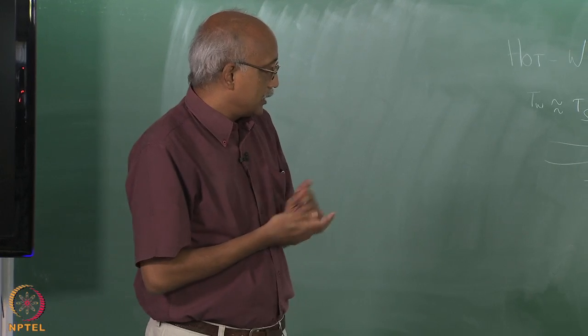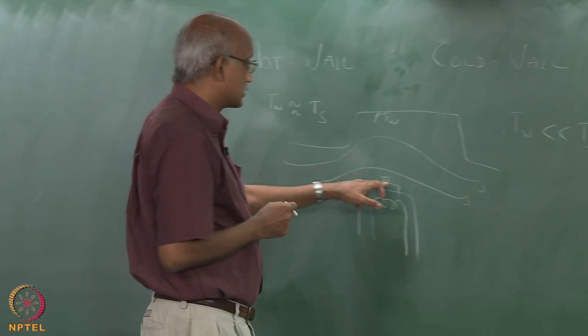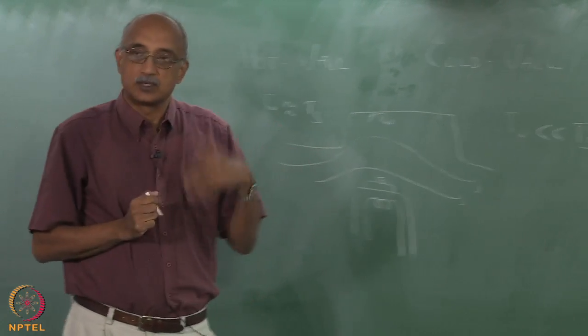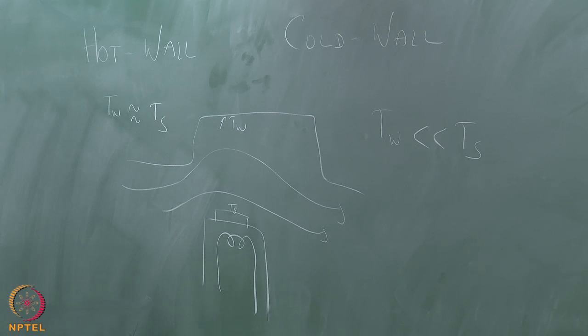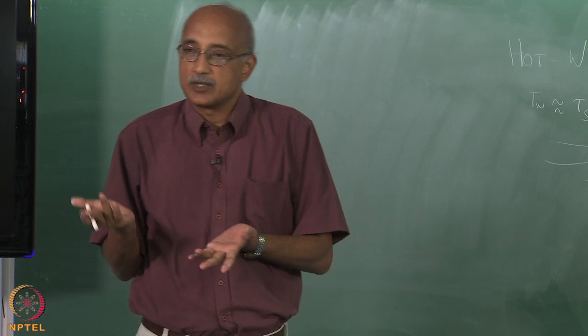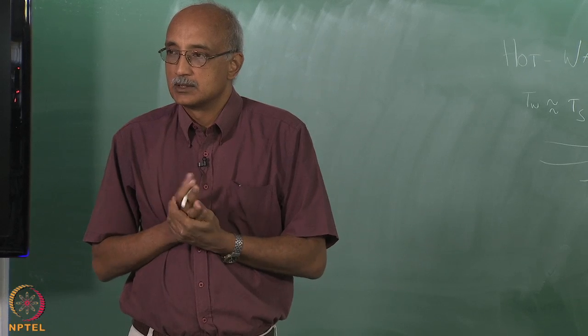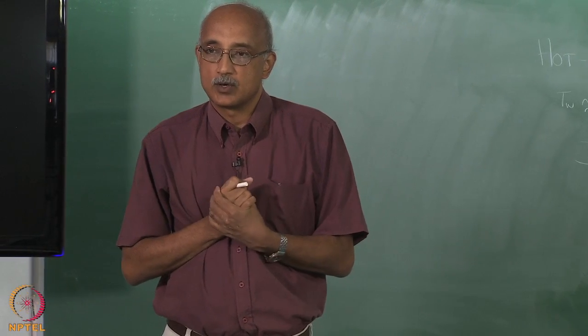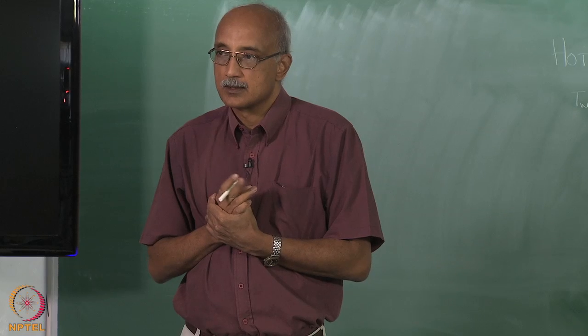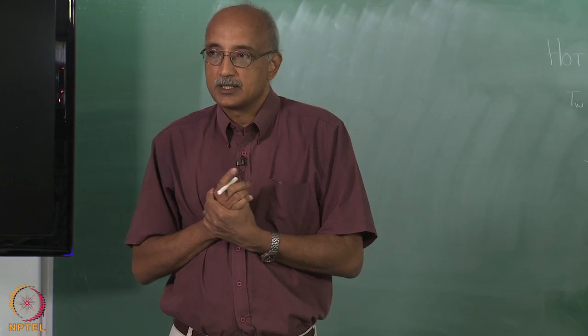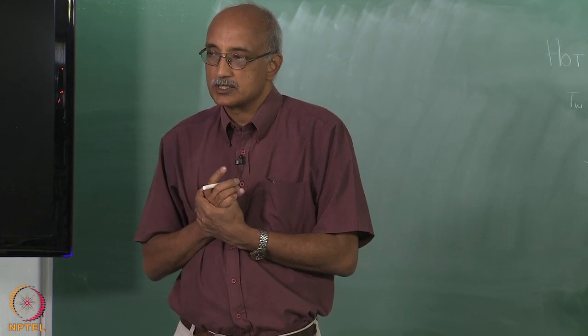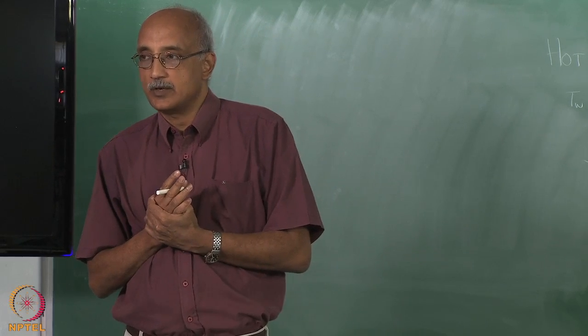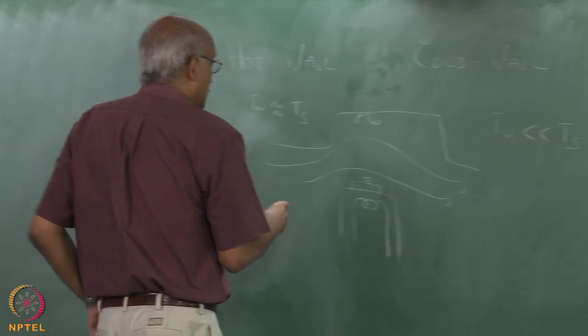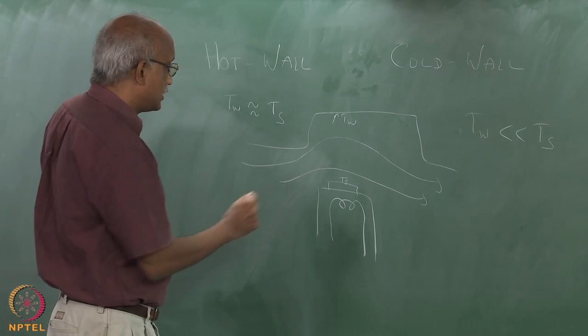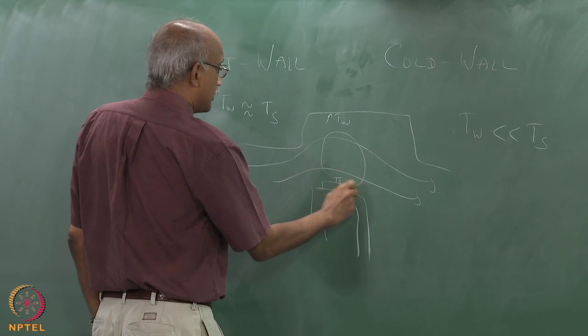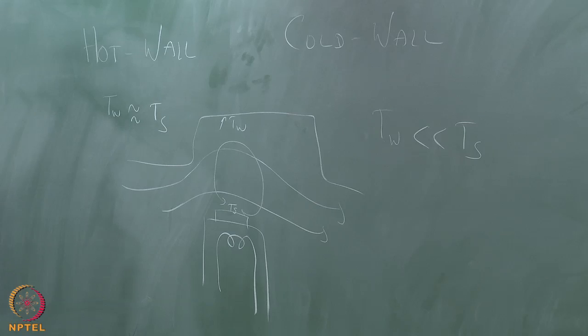When you have a case where TS is much greater than TW, in other words, a cold wall case, what happens from a flow dynamics viewpoint? What do you expect will happen? Do you think that will have an influence on how flow happens? So, there will be a big density gradient, right? The gas that's closest to the substrate will be much lighter than the gas that's far away. So, essentially what would happen? When TW is much smaller than TS, you'll start getting these recirculation loops in the system.